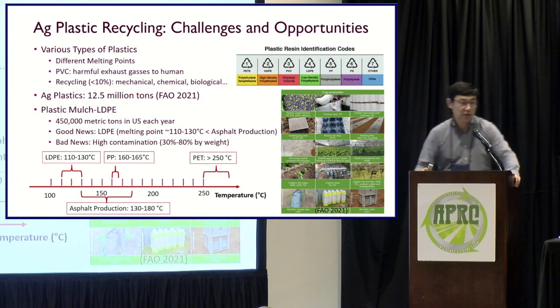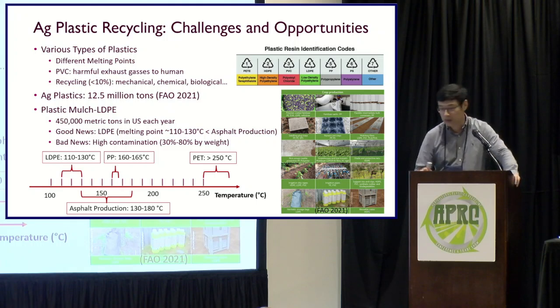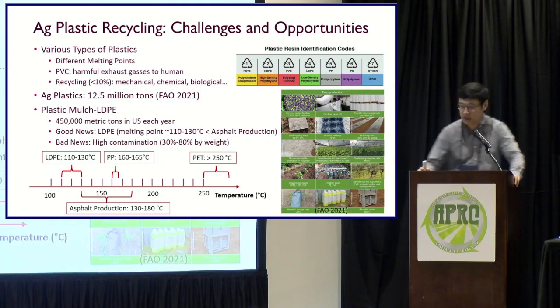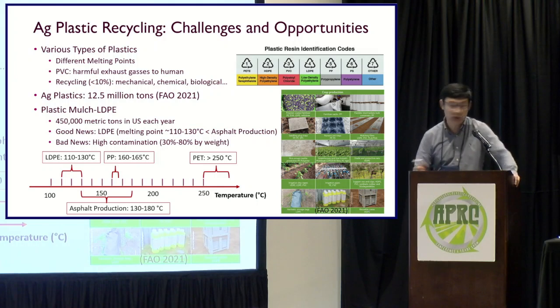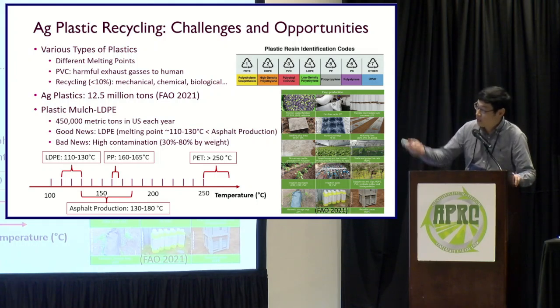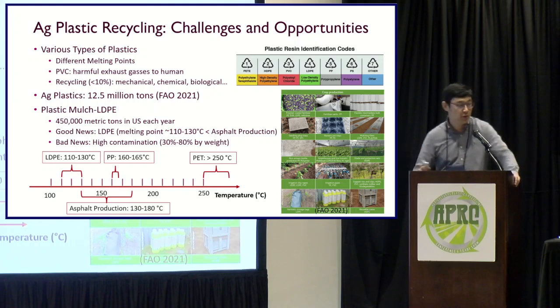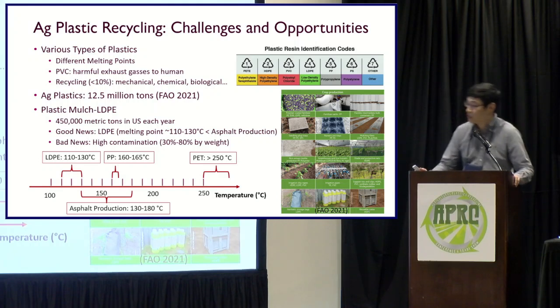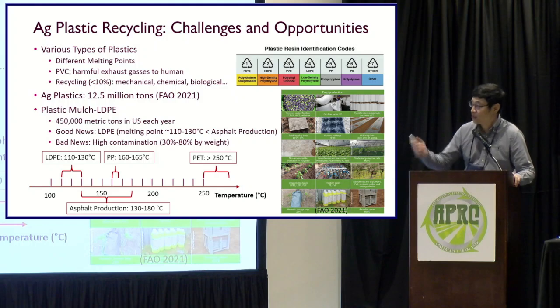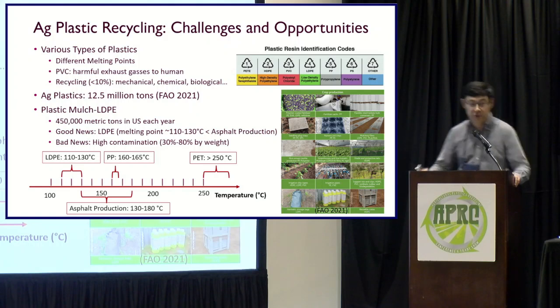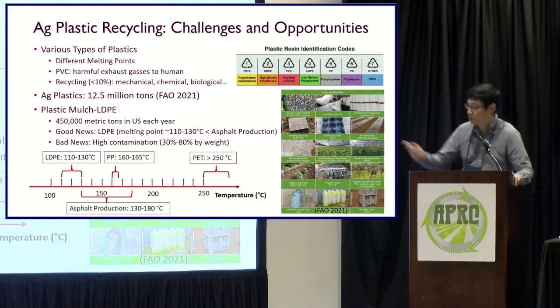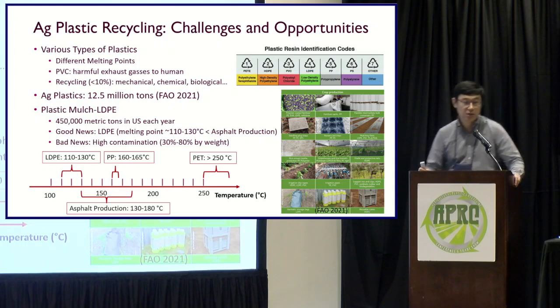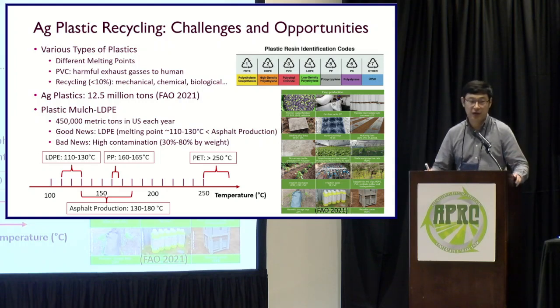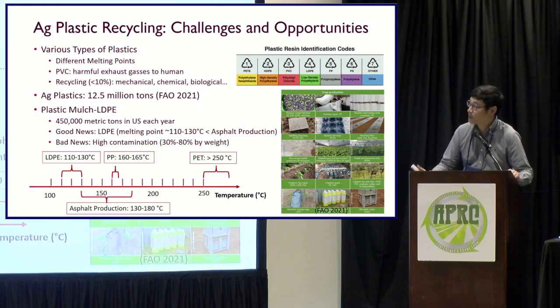Well, the challenge to use plastic in the asphalt, so we know there are different types of plastic. They have different melting points. If we look at the low density polyethylene, the melting point is between 110 to 130 degrees Celsius. And the PP is around 160 degrees Celsius, and the PET is higher than 250 degrees Celsius. As a reference, when we do the asphalt production, the production temperature is between 130 to 180 degrees Celsius. So it's around 350 Fahrenheit when we produce the asphalt mix.